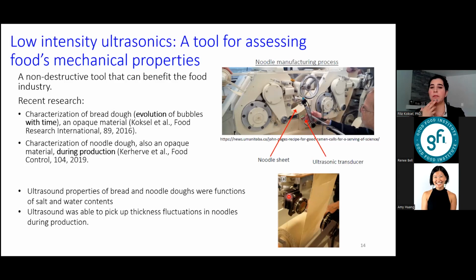And also for the noodle study, we were able to see that ultrasound was able to pick up differences in the thickness of noodles, which is a very important parameter for the noodle making industry. The advantage was that instead of measuring the thickness using a caliper, cutting a piece, we can do it in a non-contact way. And you can really see here that nothing is touching the material that's flowing in between the transducers.